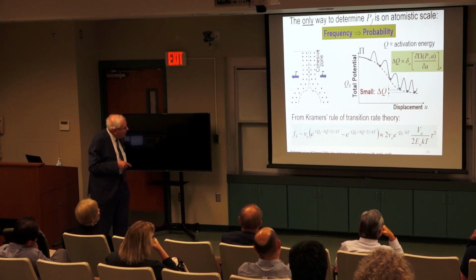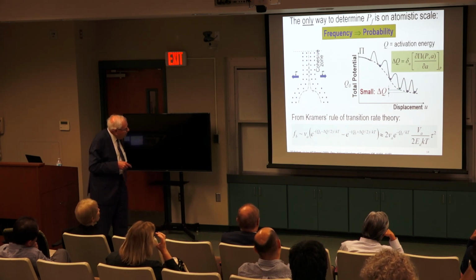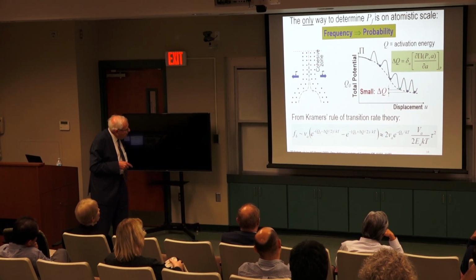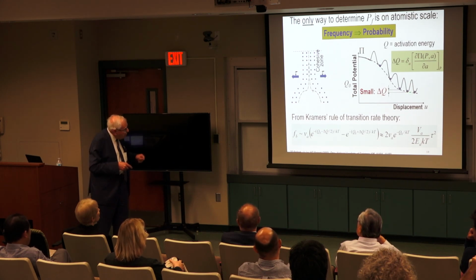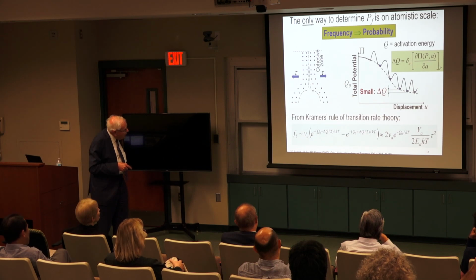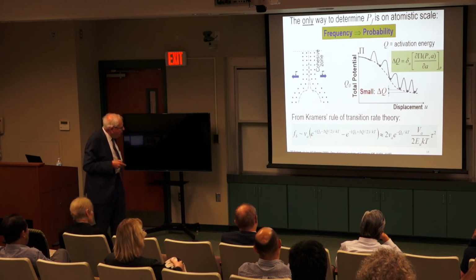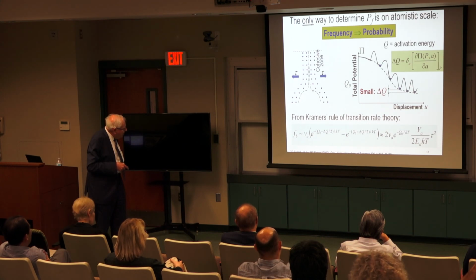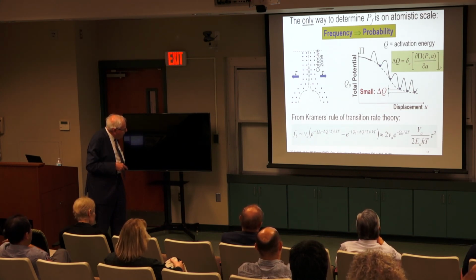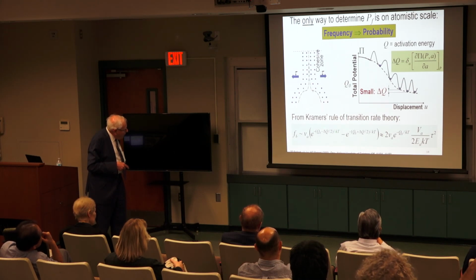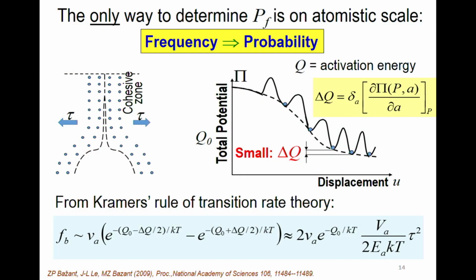Now what is happening is that we can imagine a bond rupture means that this atom gets out of equilibrium position, jumps over and comes to the lower equilibrium position. But it's happening both ways, also backwards, but the frequency forward is bigger than backward. So there is Kramers' rule in transition theory and chemical thermodynamics, used for chemical reactions, which gives you the frequency as an exponential of activation energy divided by Boltzmann constant and temperature. So for the jumps forward, the barrier is reduced by half of this, and for backwards the barrier is increased, so these are more frequent. Obviously, if these exponents are not very different, it goes to a sine hyperbolic.